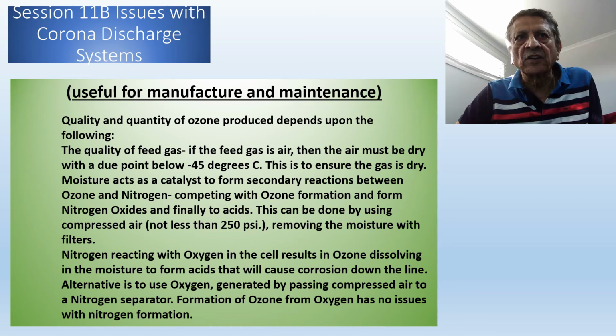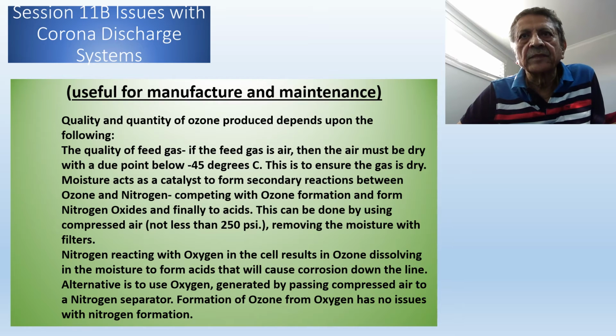This can be done by using compressed air, not less than 250 psi, removing the moisture with filters. Nitrogen reacting with oxygen in the cell results in ozone dissolving the moisture to form acids and will cause corrosion down the line. The alternative is to use oxygen generated by passing compressed air to a nitrogen separator. Formation of ozone from oxygen has no issues with nitrogen formation.